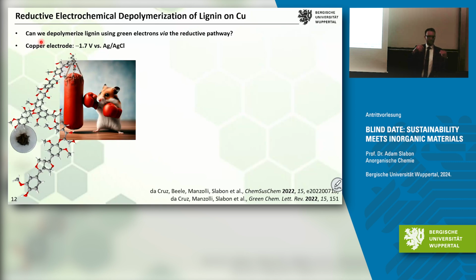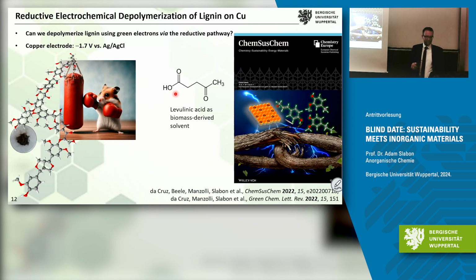So you have to find this balance between both reactions in solution, and we take this as an additive to dissolve the lignin, and then in theory it looks like this. You have your catalyst, green electrons, and in a spectacular way you break the chains of lignin.